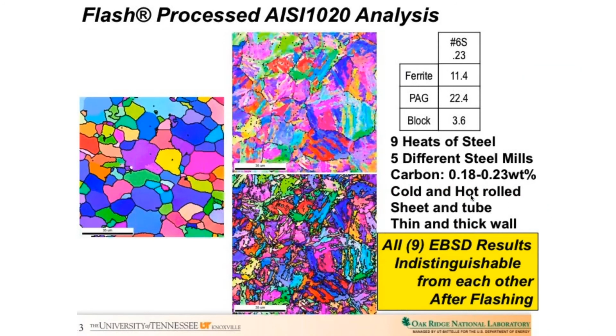Well, how easy is this to apply in a lot of places? Sometimes technology gets applied in the laboratory, and as I know Joe mentioned, you don't want it to sit on a shelf. You want this to go places. Well, how do you get it to go places? You test out different things. We took 9 heats of steel from 5 different steel mills. The carbon content ranged from 0.18 to 0.23 within the specifications of the 1020 chemistry.